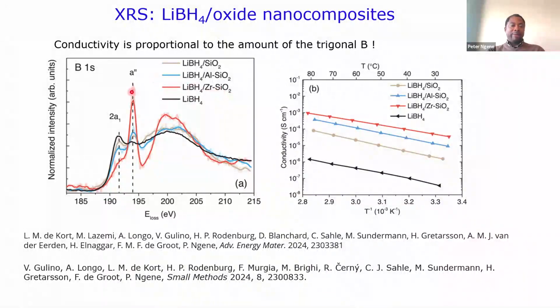material. And if we look at this, we had a kind of model experiment where we start with silica, and then we're able to cover the surface of the silica with alumina and then with zirconia. Why are we doing this? Because when you have pure silica or alumina or zirconia, because they are chemically different, they have different surface area, and then they have different kind of surface properties.